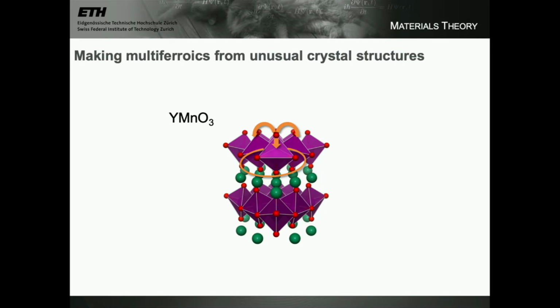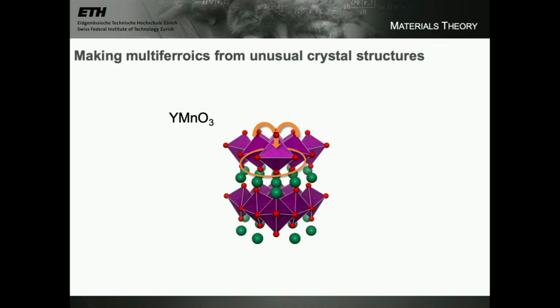Our second approach was maybe a little bit cleverer, and that was by making unusual crystal structures in which one could trick the magnetic atoms into making electric dipoles, even when they don't really want to, by virtue of the crystal structure. And here the example that I'll talk about a little bit more later is yttrium manganite. When you look at this chemical formula, probably you all think perovskite. Those of you who recently had a ceramics class, it's a typical chemical formula for a perovskite structure. But you can see it's not perovskite. It has layers of yttrium atoms separating layers of trigonally bipyramidally coordinated manganese, MnO5 trigonal bipyramids that are corner shared.